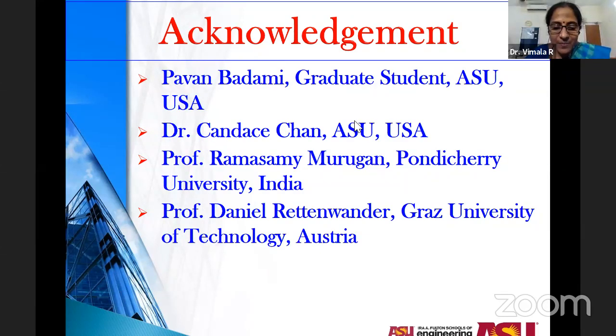Thank you, Professor Kannan. I have a couple of questions raised by the audience. Can mesoporous carbon be helpful in controlling lithium dendrite growth in lithium metal batteries? So as long as the pore can be blocked, if the sintered pellet can have higher relative density, you can avoid the dendrite. There's no way, electrochemically in the batteries, you can limit the lithium dendrite growth. So one specific thing is like putting an impervious wall. So any material which would help in sintering the pellet well without any pore structure can be used.